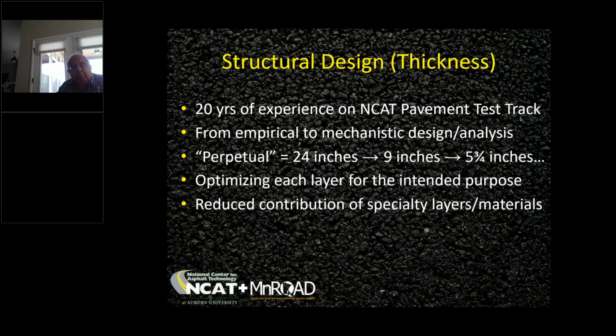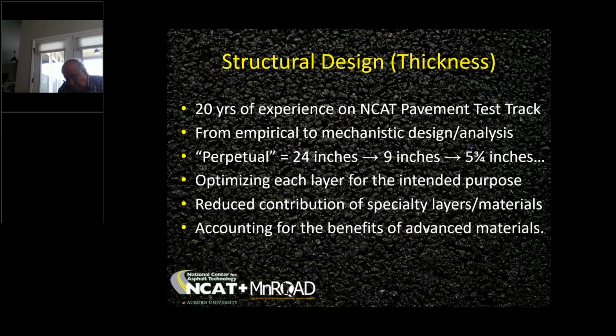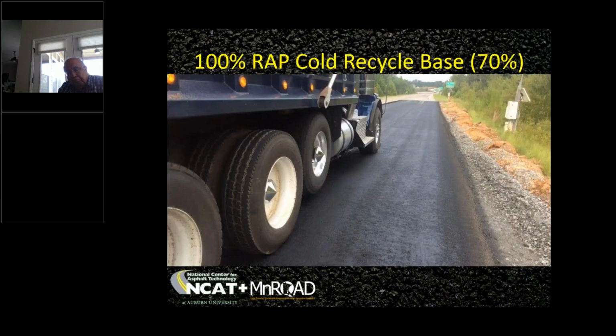We talk a lot about being able to do thinner pavements. Well, sometimes when you have specialty layers or specialty materials, you need to have a reduced layer coefficient. I mentioned porous pavements. When you have porous pavements, that has to have a significant reduction in the layer coefficient because of all the voids that are present in those mixes. And I'll talk about that more in just a minute. But a big part of thickness design is accounting for the benefit that you get from the advanced materials. Going from 24 inches to 9 inches to 5 3/4 inches, how do you quantify that? Well, we have really good guidance that's been developed from the track to help us to do that.